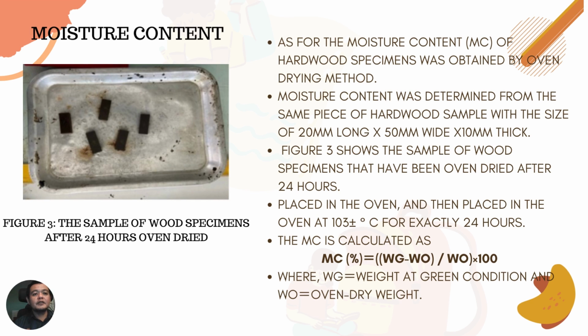As for the moisture content of the hardwood specimen, it was obtained by the oven drying method. Moisture content was determined from the same piece of hardwood sample with the size of 20 mm x 50 mm and 10 mm thick, as shown in Figure 3. So Figure 3 shows the sample of wood specimen that has been oven dried after 24 hours.